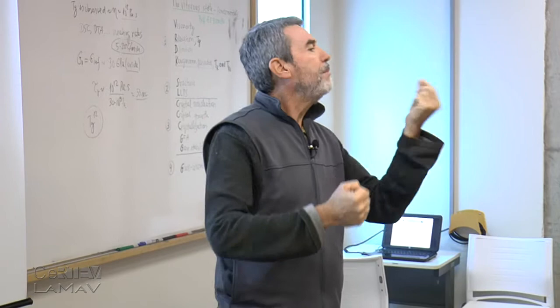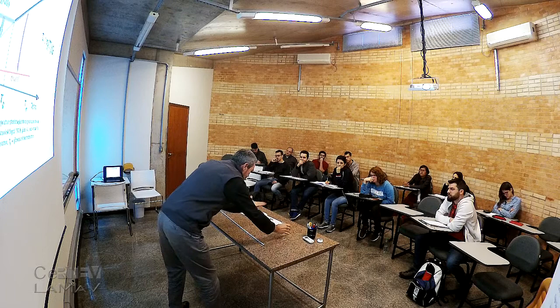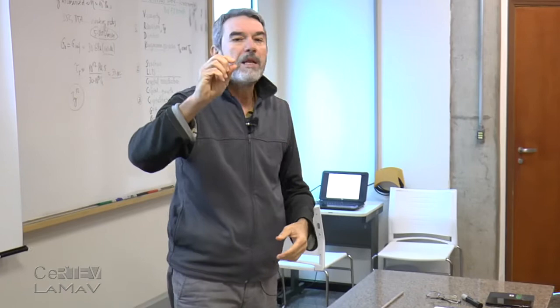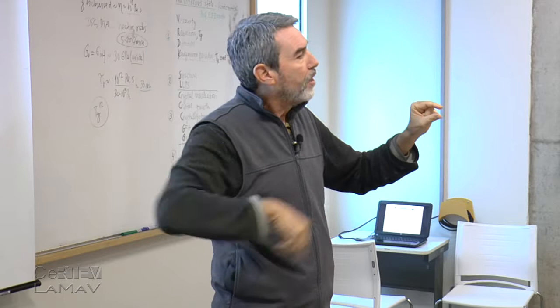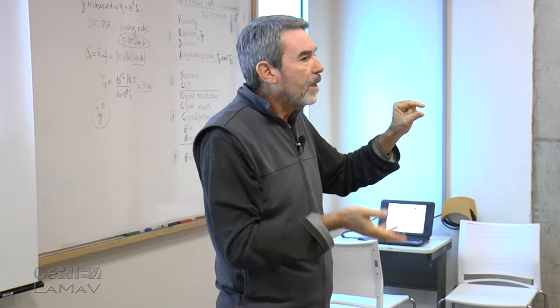So we started by doing 1 millimeter glass samples. You cast the glass in a steel plate and then you press with another steel plate, for instance. So you have a 1 millimeter glass sample, no problem. 2 millimeter glass samples, no problem. When we tried to make 9 or 10 millimeter glass samples, crystals were forming in the interior of the glass, because you cannot cool down the interior of the glass fast enough.